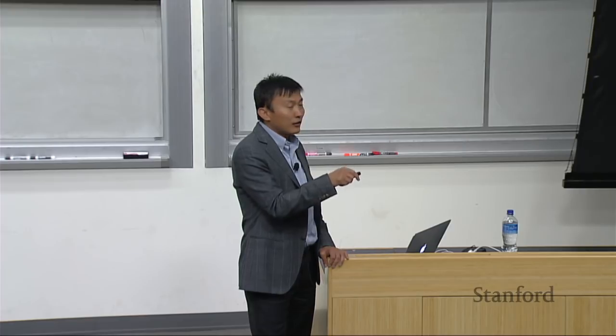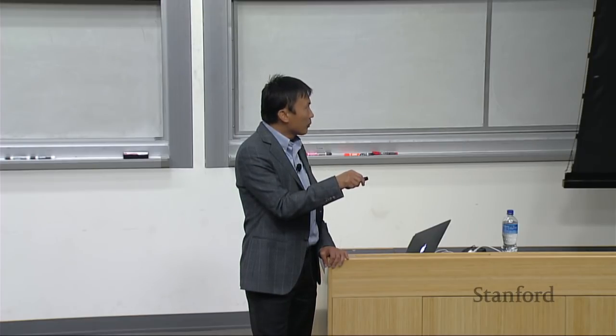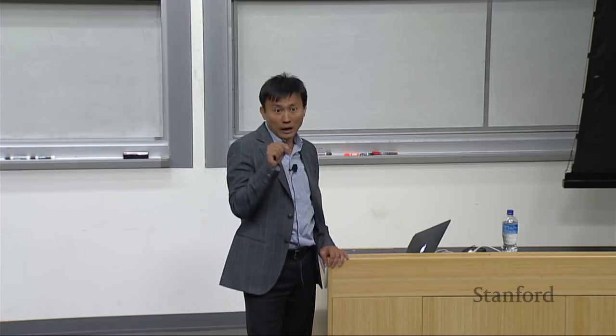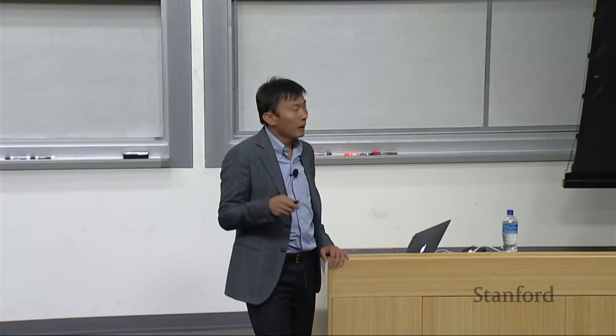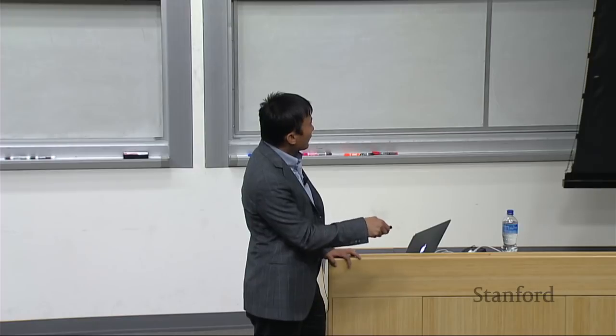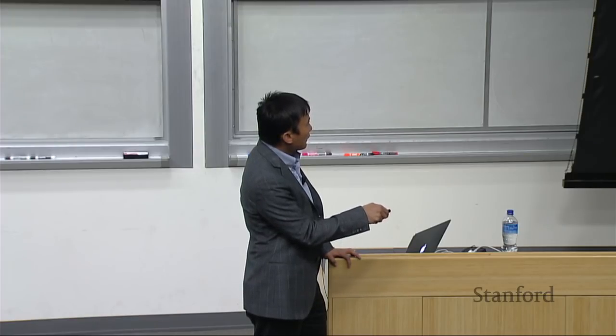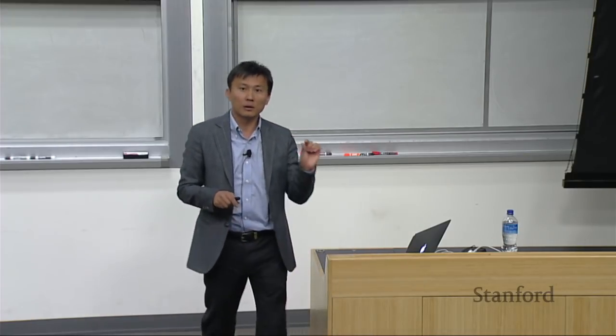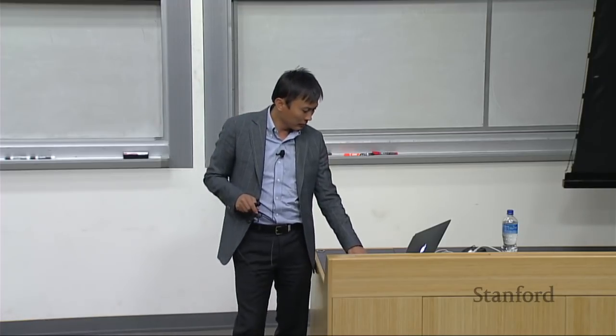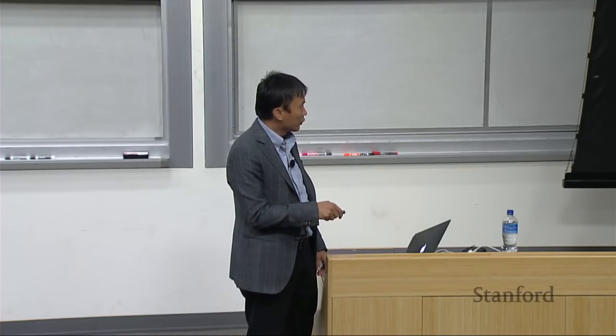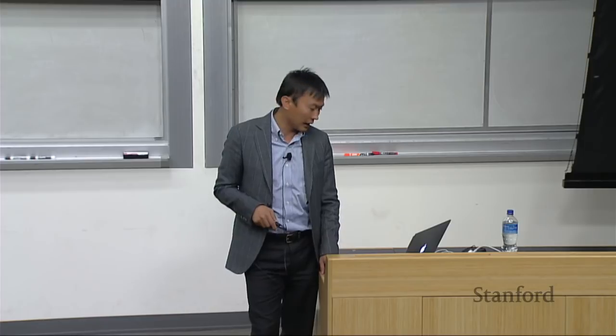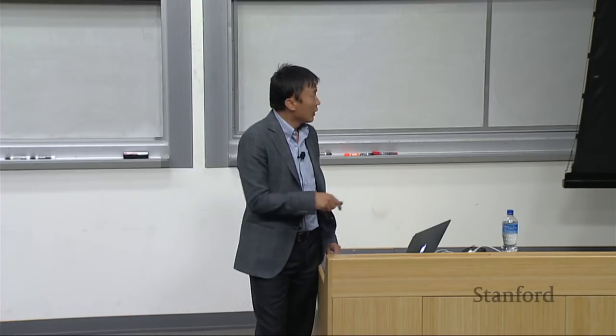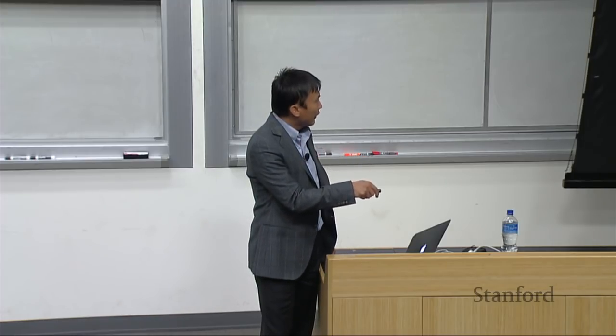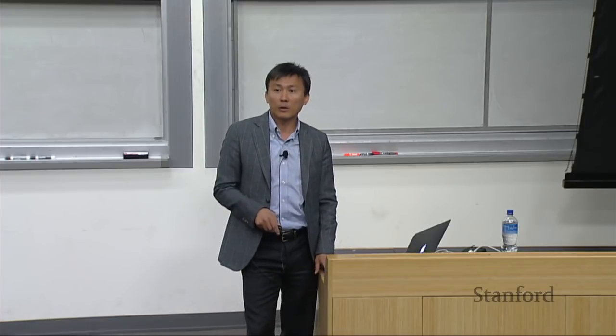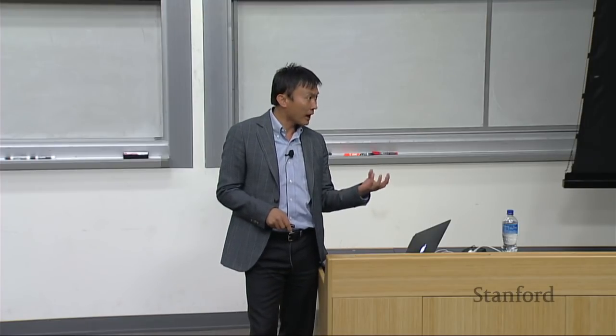This is the standard TEM. You focus the electron beam, and you see you drill a hole into this structure right away. So you cannot image them. Now with cryo-EM, you can look at the structure for 1 minute, 5 minutes, and 10 minutes. They still remain the same. And using an analytical tool called EELS, electron energy loss spectroscopy, we can confirm this is metallic lithium we are looking at. Instead of lithium ion, it's metallic lithium.